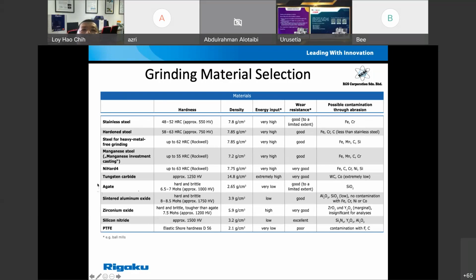And just now we showed you agate. Agate mortar is very commonly used. But if you use agate to pound some samples, you can see that you're going to have some silicon oxide in your samples. And if your sample hardness is much higher than your vessel or grinding material hardness, you get more grinding material into your samples, so you leach more contamination into your samples. This is something you need to be aware of.